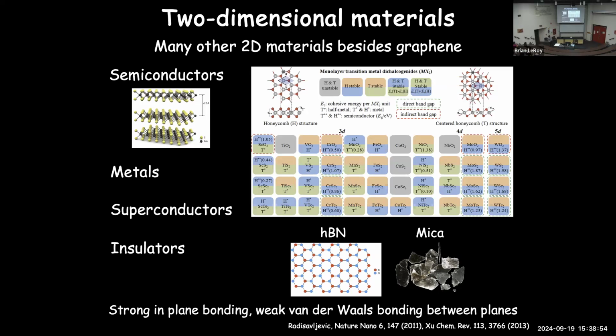In particular, there is a material here called hexagonal boron nitride. This looks just like the graphene structure, except that instead of carbon atoms, we have boron and nitrogen atoms alternating as you go around this hexagon. And because these are inequivalent atoms, unlike graphene where you have carbon, 2 equivalent atoms at the 2 different sites, you have very inequivalent atoms here, boron and nitrogen. And so there's a large band gap in this material, and it's a very good insulating material.